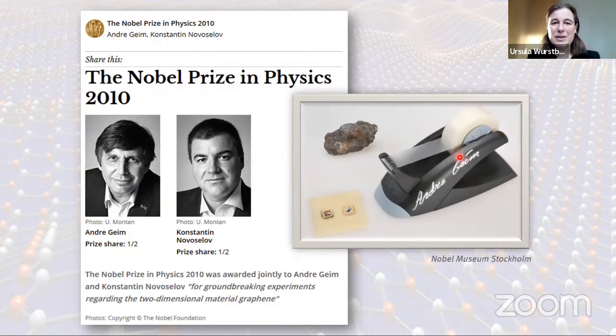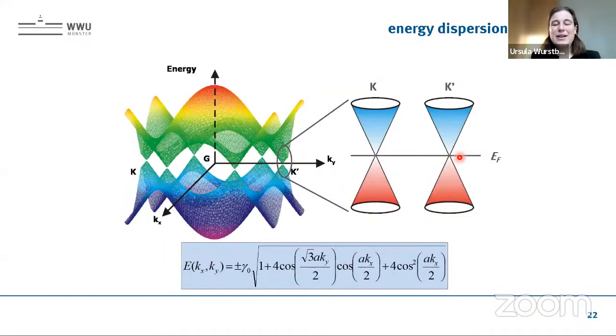So what is so cool and so fascinating about graphene? Well, first of all, the band structure. If you have a look at the band structure, which can be calculated like in a textbook because of the simplicity of having the same atoms in the lattice, with an sp2 hybridization, we just need to take into account the pi bonds, the pi states, which create the band structure because of the overlap. And if you do the math, you end up with this energy dispersion.